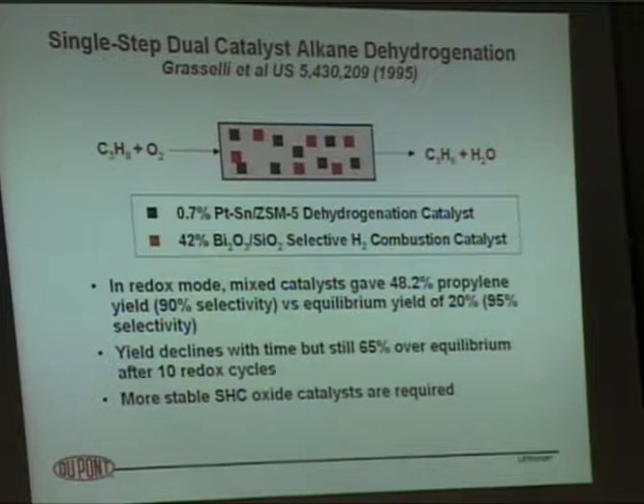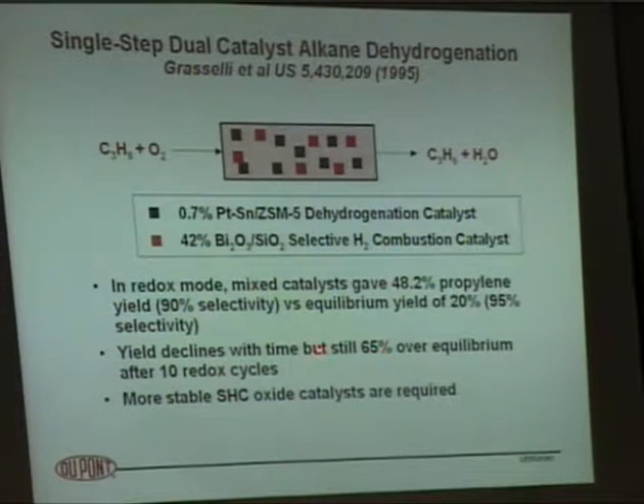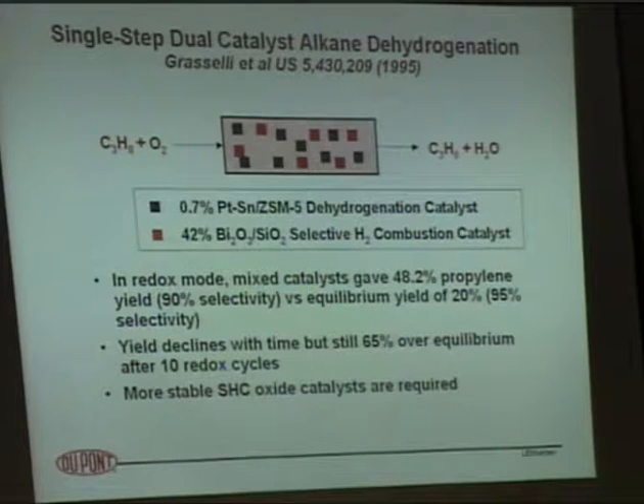So this was a very significant advance, not a significant decrease in selectivity, 95 to 90%, but much higher conversion in that process. The only problem is you're operating a catalyst that really wants to be reduced in an oxidizing environment. So the catalyst slowly gets oxidized, or the oxidation catalyst gets reduced, and he loses activity. So Bob comments that we still have some work to do there, but he's optimistic that they can find a system that ultimately might work in a single reactor system to go high yield to propylene from propane.